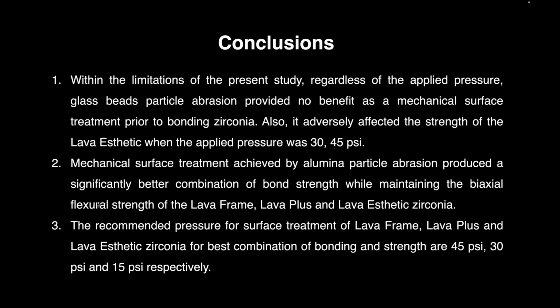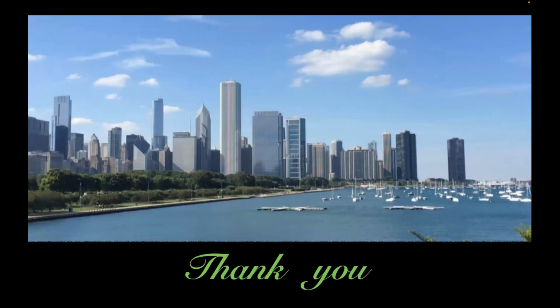The recommended pressure based on this study for surface treatment of Lava Frame, Lava Plus, and Lava Esthetic zirconia, the 3Y, reduced alumina, and the 5Y zirconia, for the best combination of bonding and strengths are 45 psi, 30 psi, and 15 psi respectively. Thank you very much, and I'm open to any questions the audience might have.